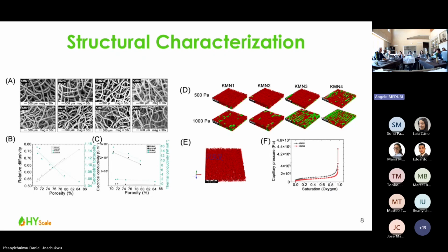That means we have straight-through paths through the material. And the relative diffusivity increases as the porosity increases. This is clear. So we had 4 different ones with nickel and also 4 different knitted meshes with Inconel, as we tried this also as a more corrosion-resistant material.